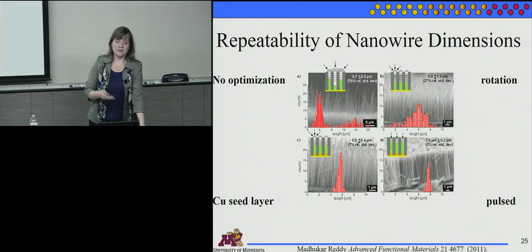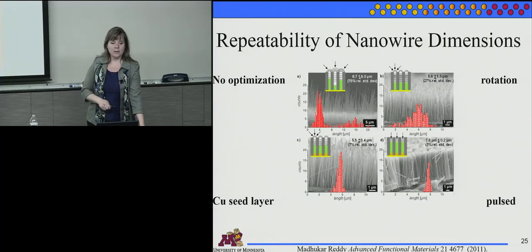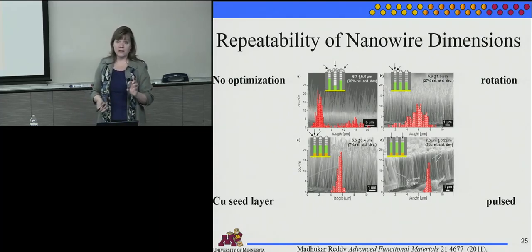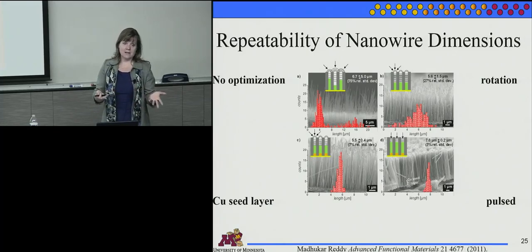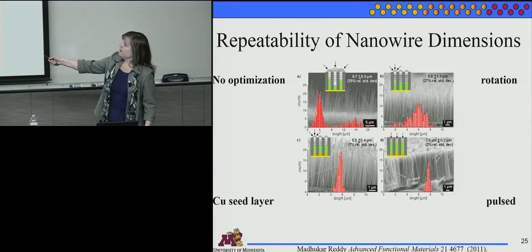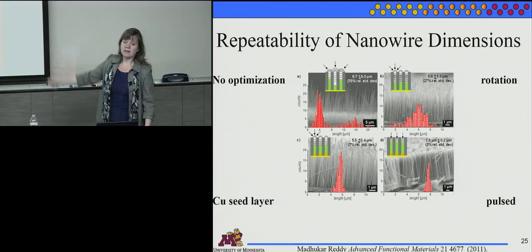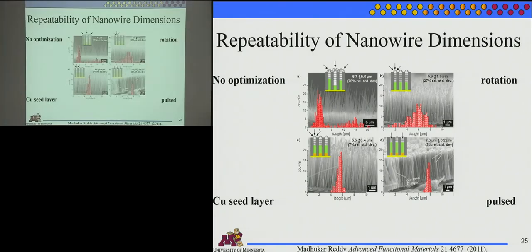So the first thing we had to do, which isn't on here, is find a complexing agent. And we have a paper on that. I should have put it here. But basically, you can keep the gallium in solution if you put citrate with it, so it stays dissolved. And then you want to use a rotating disc electrode. So you actually spin the sample itself instead of having a stir bar in the middle of the beaker or at the bottom of the beaker. You bring the solution up and have it rinse past the pores, so you keep a homogeneous diffusion layer outside the pores. And then you get a Gaussian distribution at least, but it's 27% relative standard deviation, not so great.